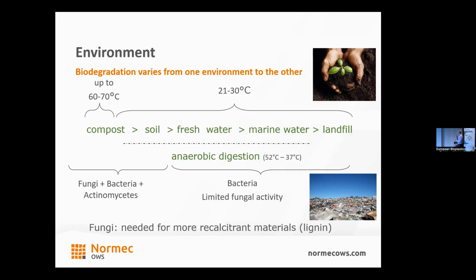Also, they are needed for degradation of lignin, this natural material, which can only be degraded due to the activity of fungi. For home composting, you have lower temperatures, so that's already one reason why the degradation is going on slower. And then soil is less aggressive compared to these two. The main reason is that bacteria are present, but not at as high a concentration as in compost, and also the low temperatures. Fresh water and marine seem in general to be less aggressive when there is a need for fungi for degradation, as in these environments fungi are present, but they are not as active as in soil and compost.